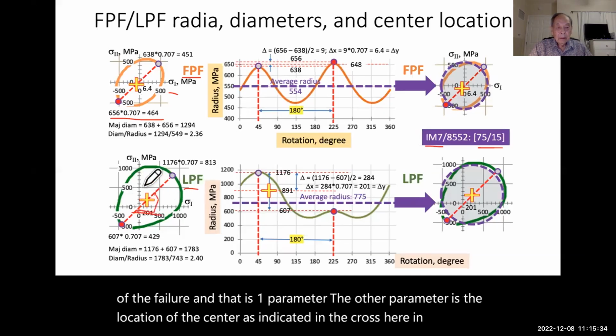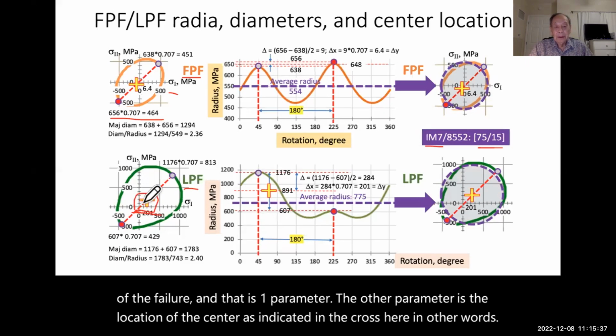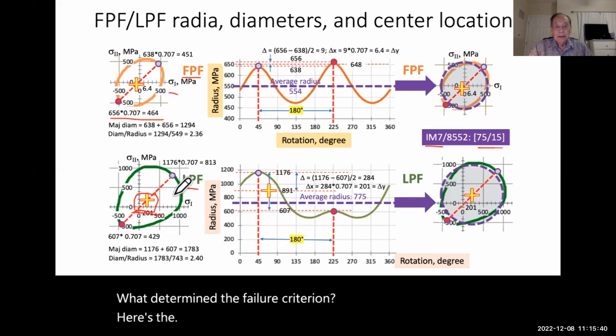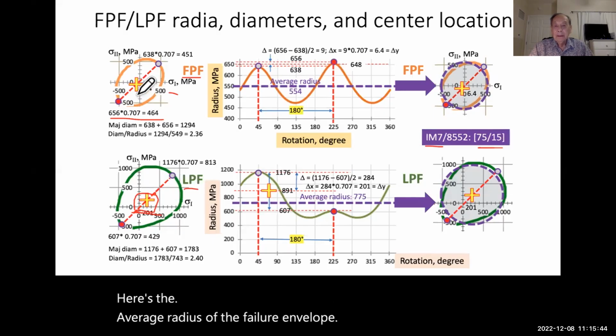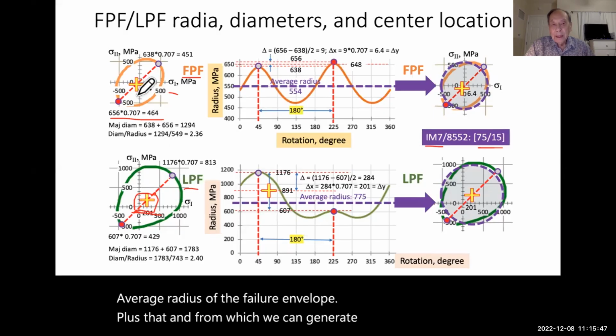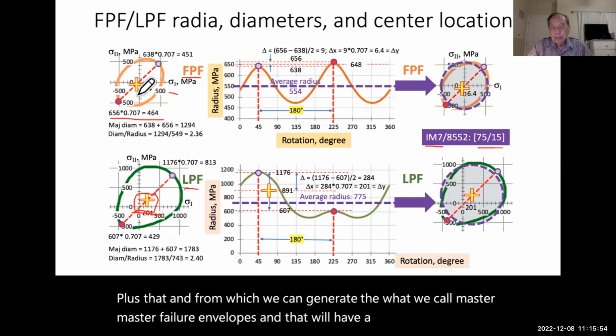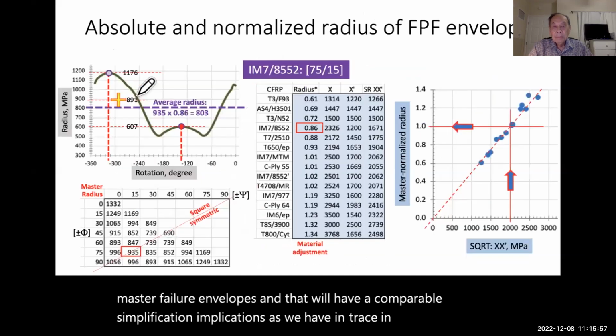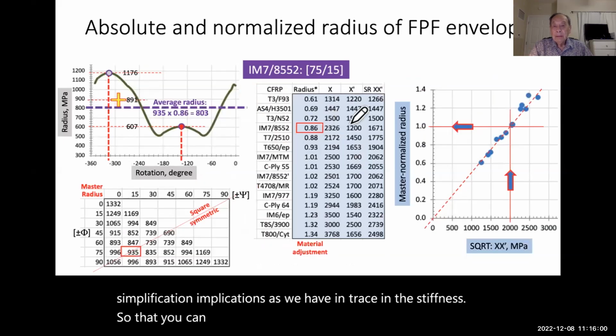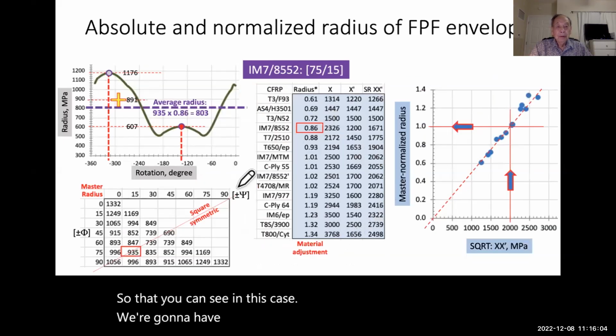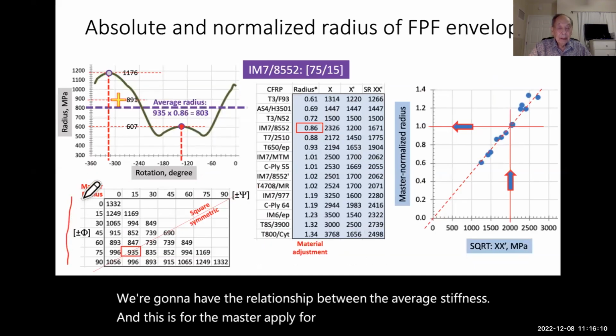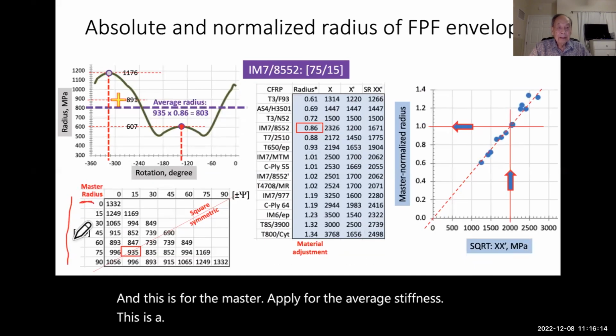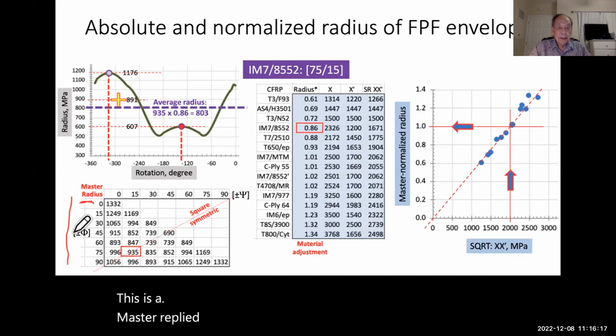In other words, what determines the failure criterion is the average radius of the failure envelope plus the center, from which we can generate what we call master failure envelopes, and that will have comparable simplification implications as we have with trace in the stiffness. So you can see in this case, we can have the relationship between the average stiffness, and this is for the master ply, for the average stiffness. This is a master ply radius, and this is plotted against the two angles, plus minus phi and plus minus psi.